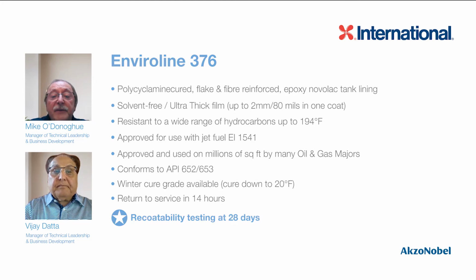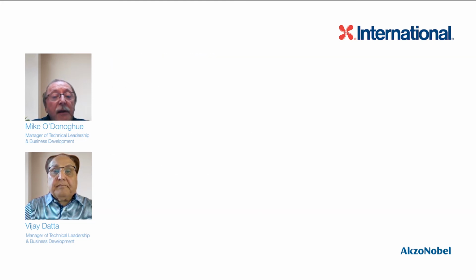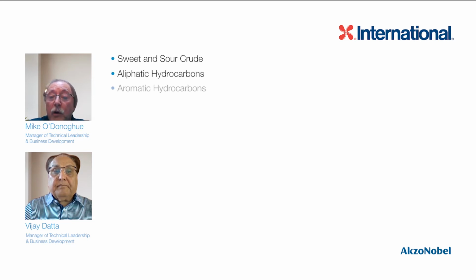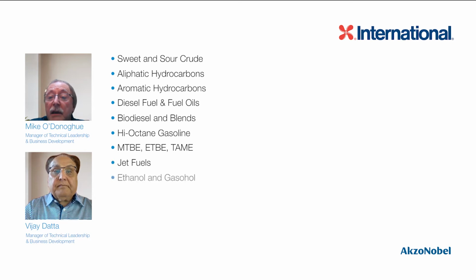We also look at 376 with the chemical resistance being very high, because the cross-link density that you pointed out earlier, Vijay, is very high. You've got short cross-links. So 376 will handle a variety of different chemicals, sweet and sour crude, especially important, say, for example, the oil patch where I hail from, aliphatic hydrocarbons, aromatic hydrocarbons, diesel fuel, biodiesel in the blends, jet fuels, a very large array of chemical resistance from Enviroline 376.